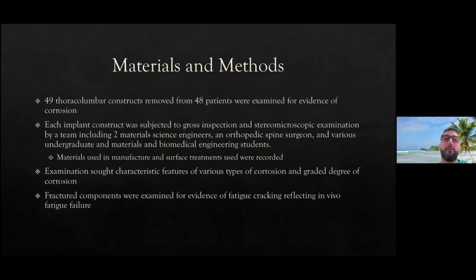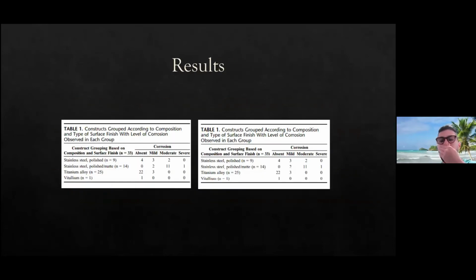And so basically, they removed 49 thoracolumbar constructs from patients, and they subjected them to gross inspection and microscopic examination. And they had a bunch of people look at them: material science engineers, orthopedic spine surgeons, and they looked for types of corrosion and whether there were fractured components, and they examined those fractured components. And this is basically what they found. The summary of these results is that stainless steel had a significant amount of corrosion. Matte stainless steel had more corrosion than polished stainless steel.